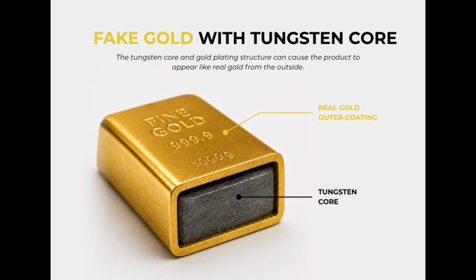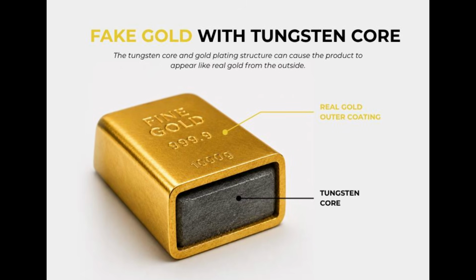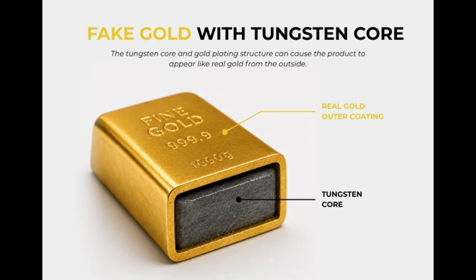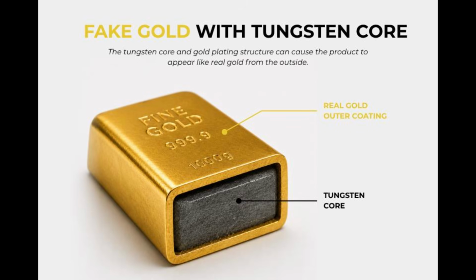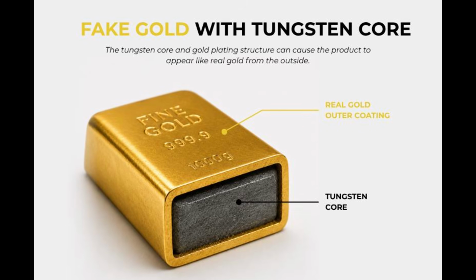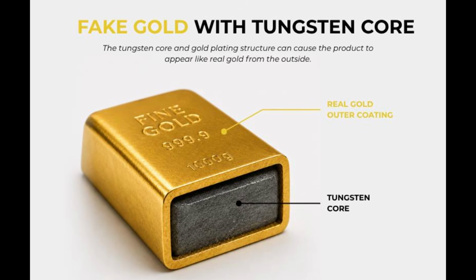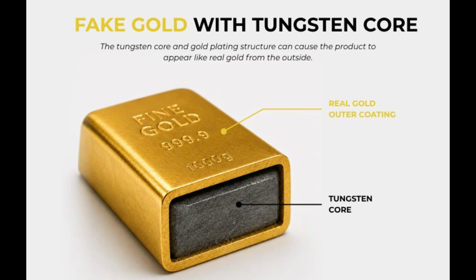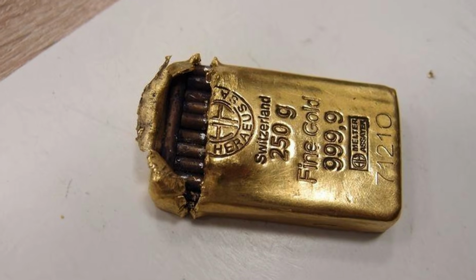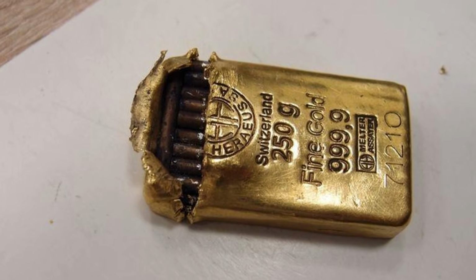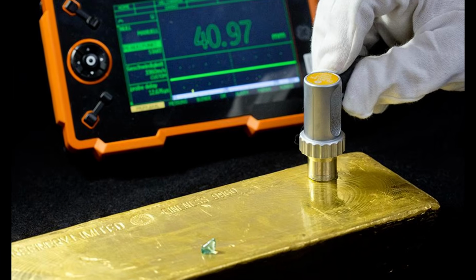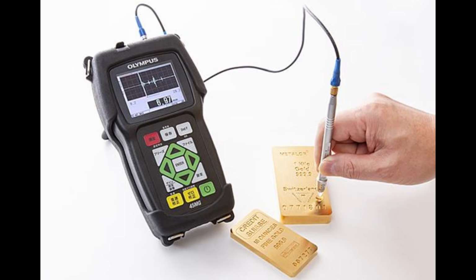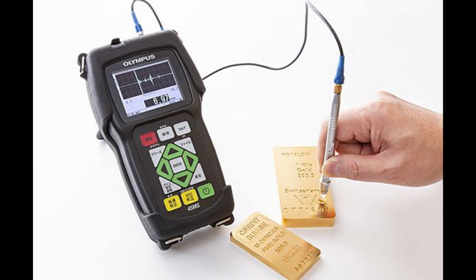Gold and tungsten transmit sound differently. An ultrasonic probe sends high-frequency sound through the bar and measures the returning signal. A foreign core, void, or internal inconsistency can produce a result that does not match solid gold. X-ray fluorescence can analyze surface composition. Conductivity testing, eddy current methods, density measurements, ultrasound, and other techniques add different layers of evidence. The appropriate combination depends on the product and suspected problem.